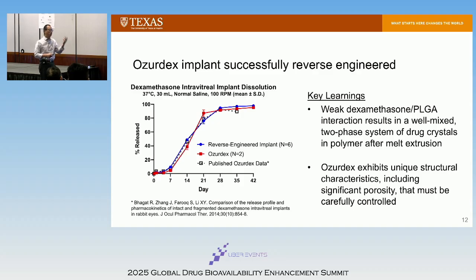Early on, we do normal saline because normal saline gave us about a month dissolution. If I do it in PBS, right, phosphate buffer 7.4, that's more bio-relevant. And that run will go over 3 months. And it's hard to do research when you don't get feedback every 3 months. So having done this, we're actually very proud. It took us about 9 months to really figure out this whole process.